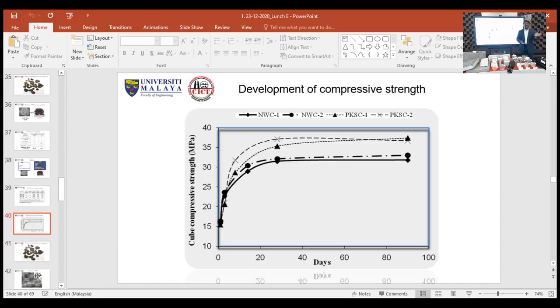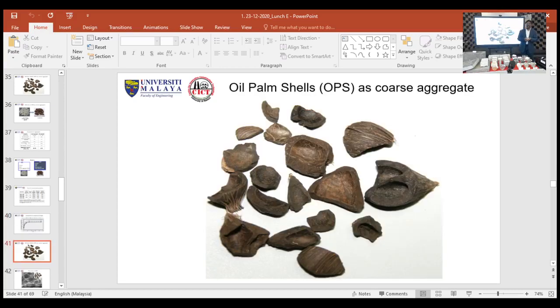And this is the graph of the development of the compressive strength that you see here over a period of 90 days. After 28 days, normally the strength development is not high, as we know. Most of those who are in the civil engineering field would know that. And as I explained before, how do we enhance the bond? Because the shell has convex and concave surfaces, it's not easy for us to get it bonded inside the cement mortar easily.